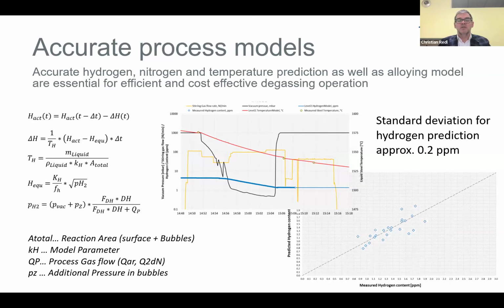And of course, you always try to hit your target content as close as possible. And this, of course, helps if you have a very good process calculation. This might also save you some samples in between, so that you do not have to measure some intermediate result during the vacuum treatment. So the standard deviation for hydrogen prediction is nowadays approximately 0.2 ppm.